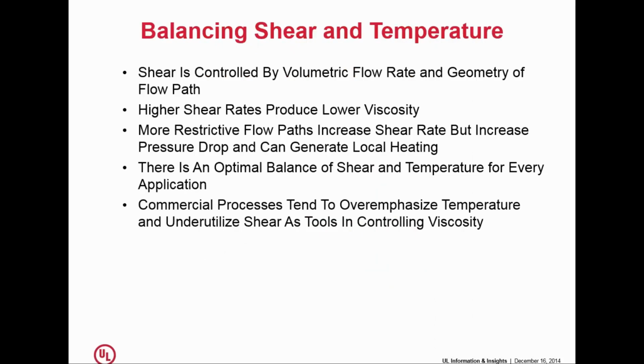As I mentioned, developing a process is really the business of balancing shear and temperature. Shear is controlled by the rate at which the material flows and the geometry of the flow path. Higher shear rates give you lower viscosity, which is another good way of keeping the viscosity down to where you can manage it. And there's always an optimal balance of shear and temperature for every application. In my experience, commercial processes tend to overemphasize the role of temperature and underutilize shear in controlling viscosity.